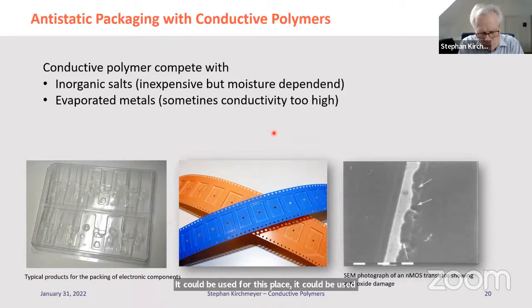And the big motivation for using it with chips instead of others like metallization and, for example, carbon black was, metallization is too conductive on the one hand. So discharge is going too fast, and it could also lead to destruction of the discrete components. And carbon black has the problem that sometimes it ablates and forms bridges between the little legs of a chip, and it has a shortcut. And the last one is inorganic salts. They're very inexpensive, but they are moisture dependent. They need water to have their antistatic